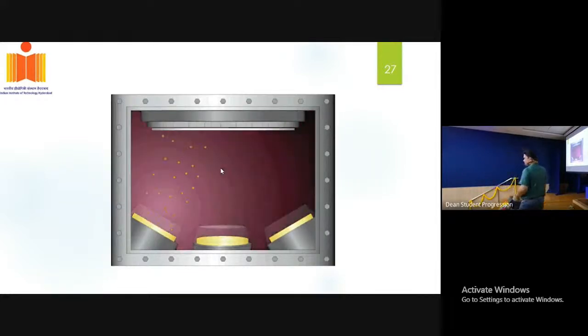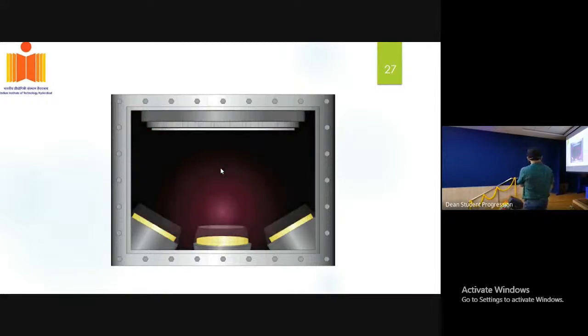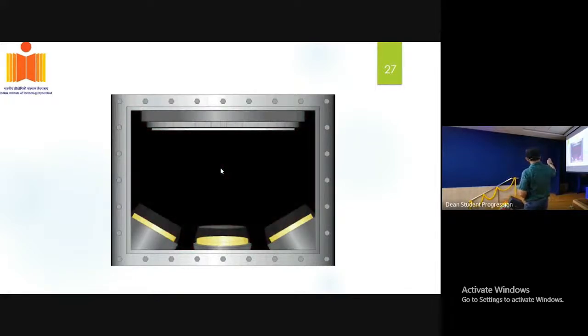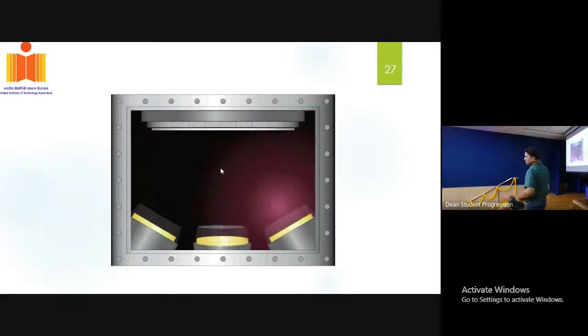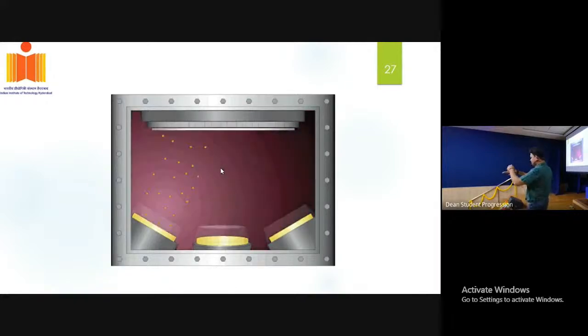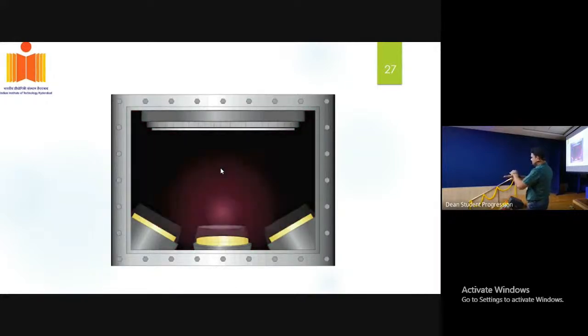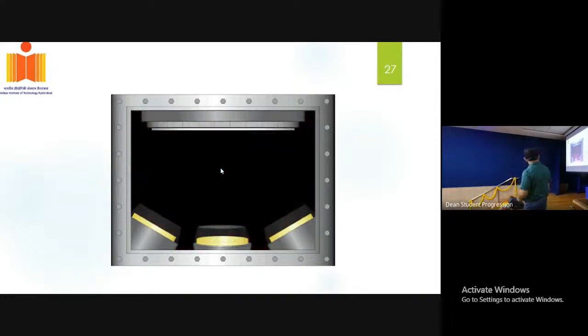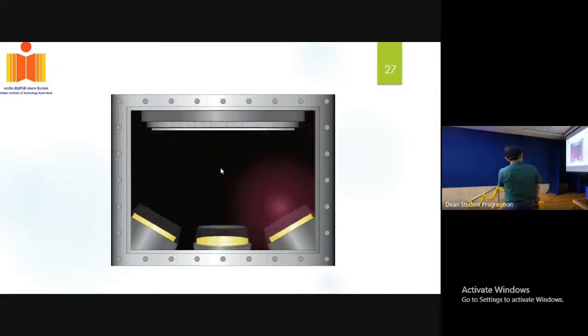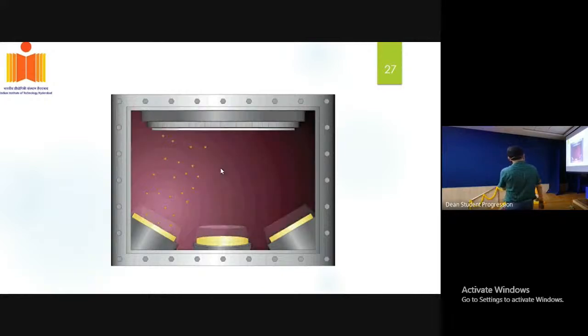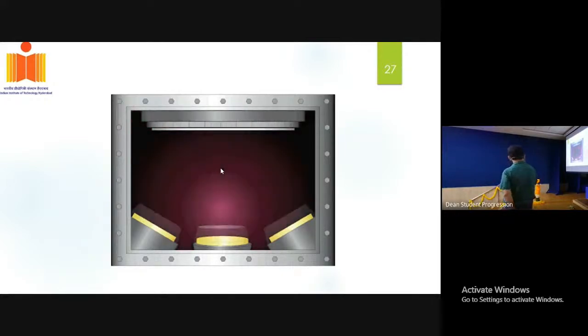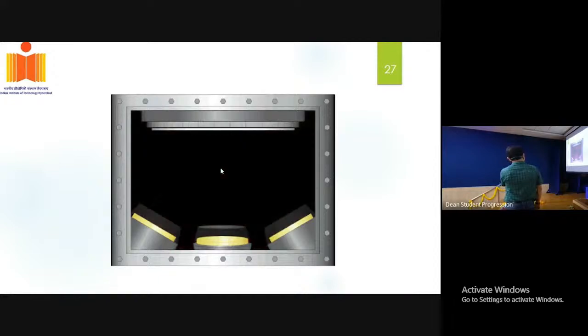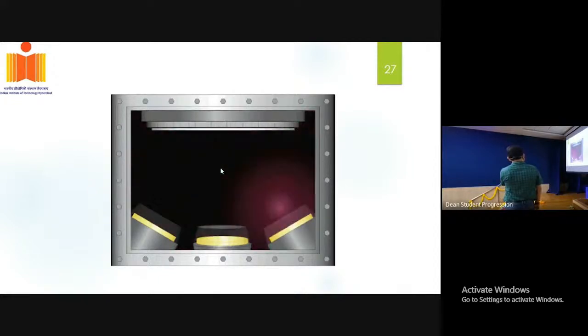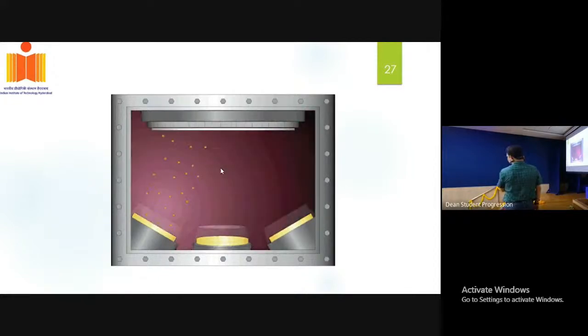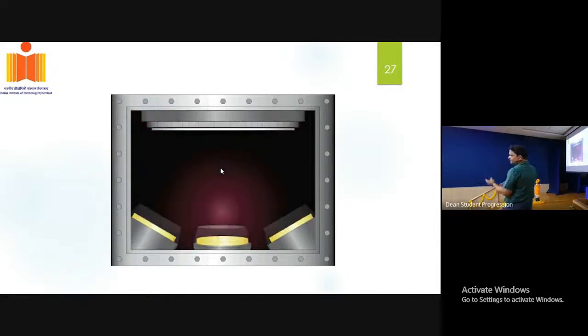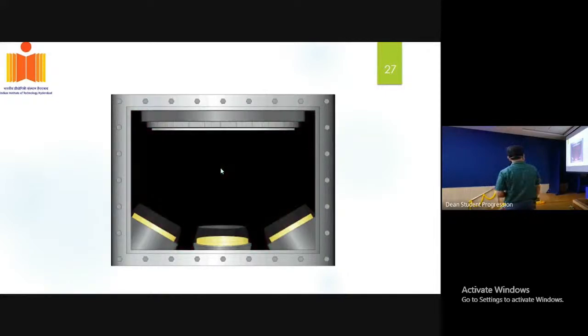So this is the confocal arrangement. That means that we have to arrange your target material at some angle. That's why it's called confocal arrangement. You can also do the direct sputtering from top to bottom, where the atoms directly go and deposit. The pink color one that you are seeing is basically the argon plasma. The small things are the atoms that are ejected from the target material and they will go and deposit on the substrate, whereas the substrate is rotating and you can also apply the temperature to the substrate.